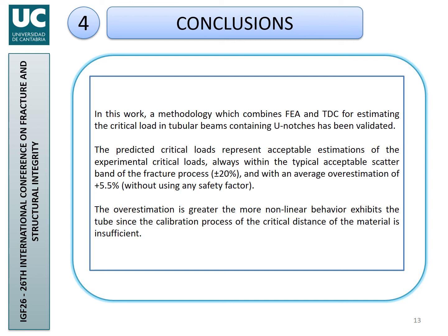And another thing which is important to mention is that the overestimation is greater in those tubes experiencing more nonlinear behavior. So the more nonlinear the behavior is, the lower the final accuracy, which is normal if we take into account that the theory of critical distances, as it has been used here, is based on linear elastic assumptions.